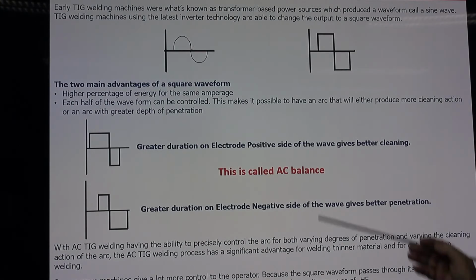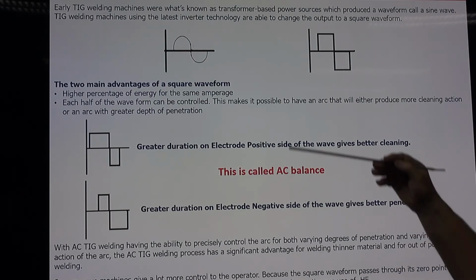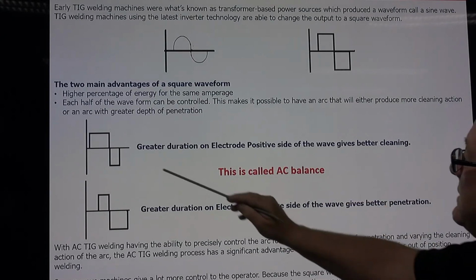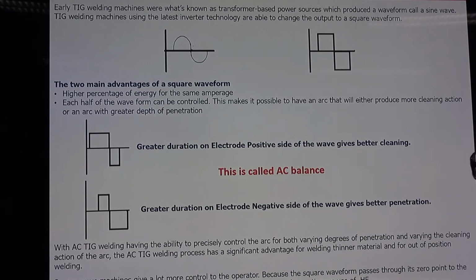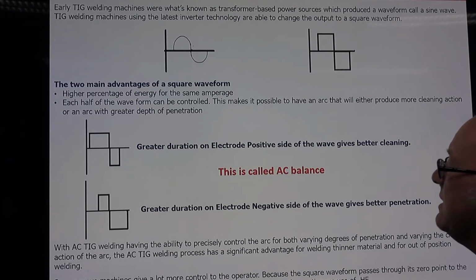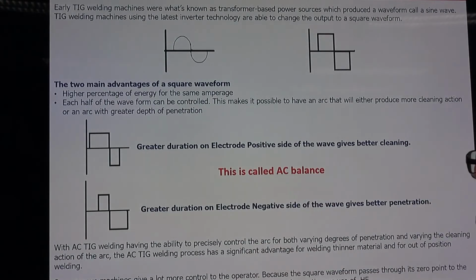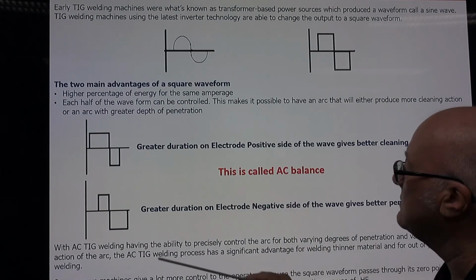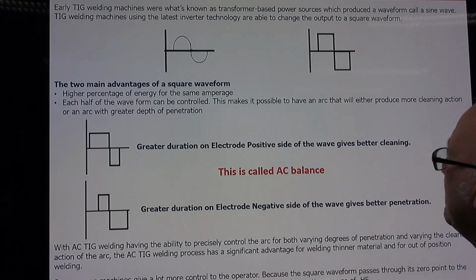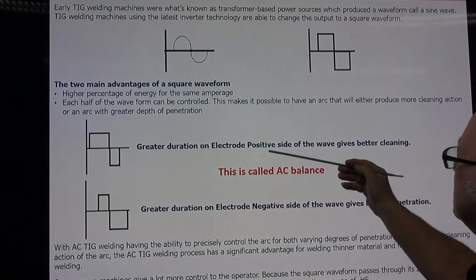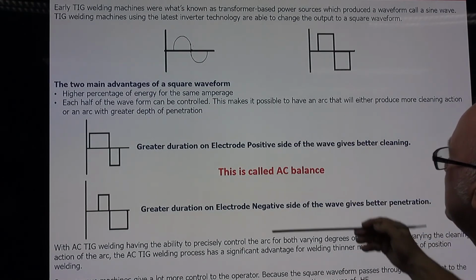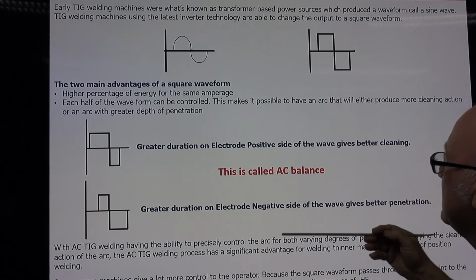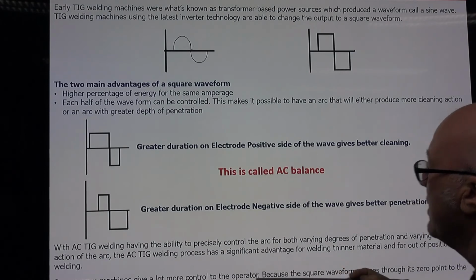The next biggest advantage is that we can play with the AC balance. This is the adjustable dial on the front, which I've gone through on the machine itself. In doing this, we can change the way that the energy goes into the workpiece and the tungsten, and what it can do for us. First and foremost, we can make the top half stay on a bit longer, which is electrode positive, and this gives us more cleaning. So when we're using dirtier outside aluminiums, etc., we can use the more cleaning cycle and do a better job. But just be aware that when you're using it on this side, the tungsten positive side gives a higher energy to the tungsten, and you have the possibility of a tungsten overheat. So just be aware of that.